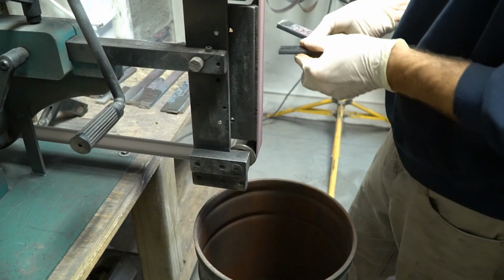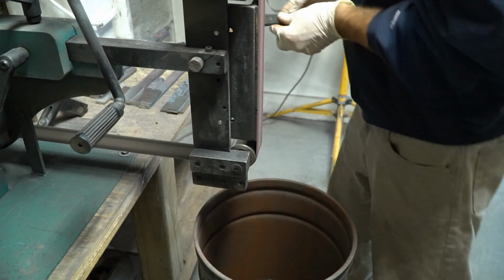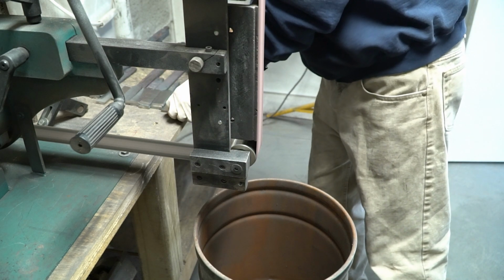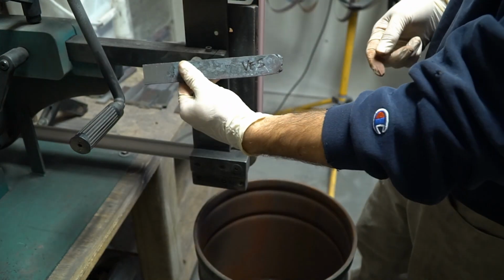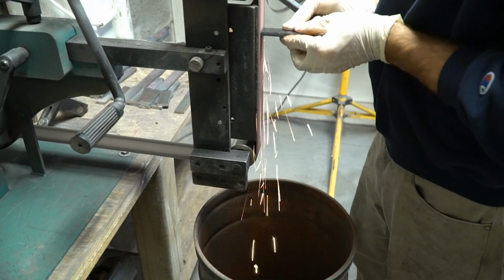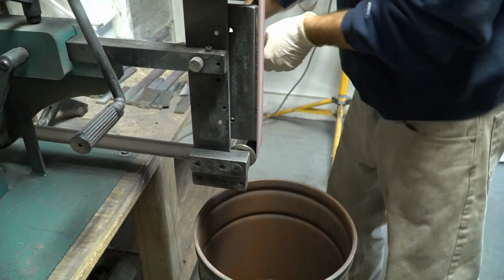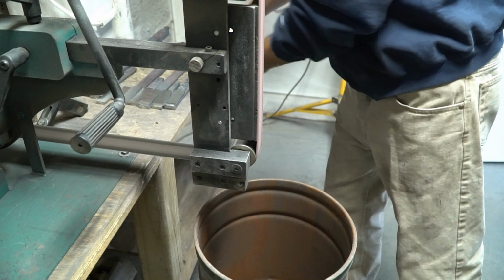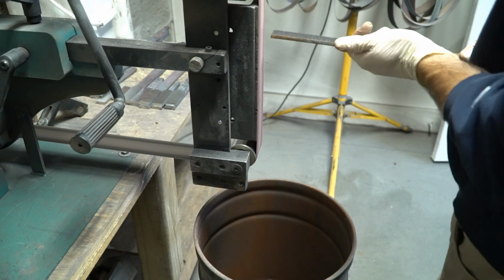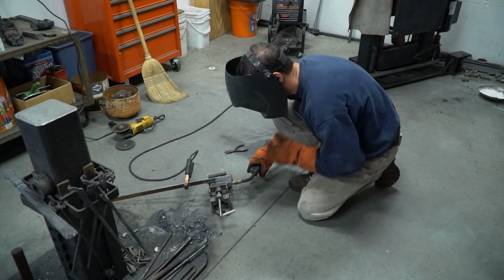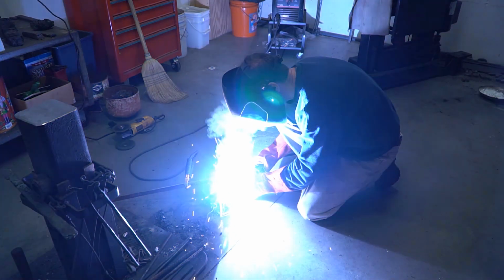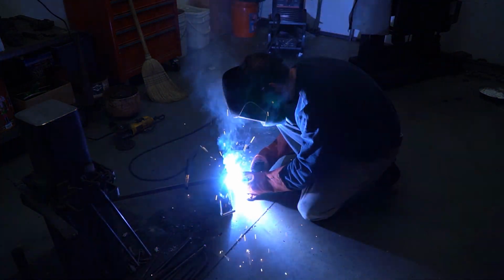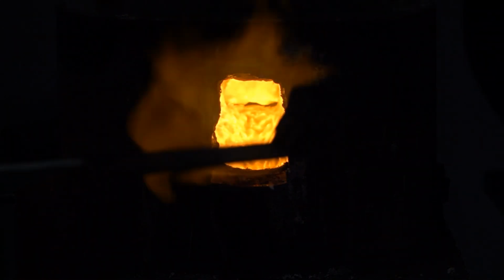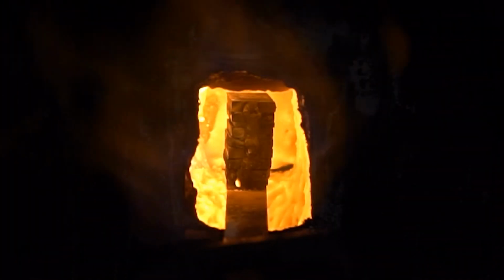Another important step that you can do at the same time that you clean up the bars in the grinder is to notice the sparks that come from the bars. The bars that are higher in carbon will show significantly more sparks. The plan is to forge weld all the bars together and then draw them out and etch them in acid to see what contrast they yield.